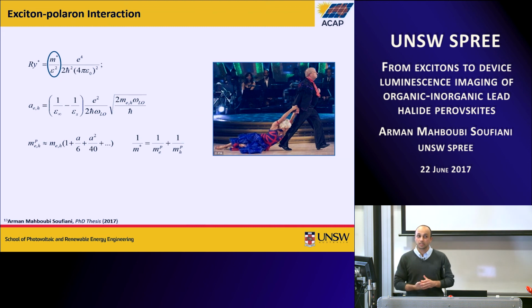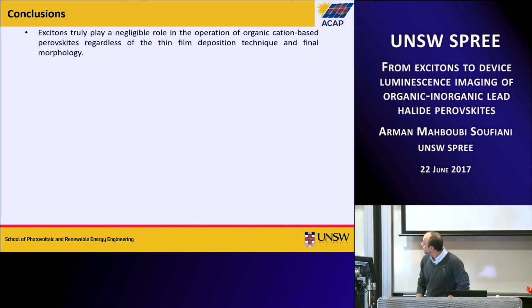And this polaronic effect is one of the reasons that the charge carrier mobility in perovskite is limited when you compare it to, for instance, gallium arsenide. Anyhow, I hope that I have convinced you. So the binding energy that I showed you was around 13, 16, and all these measurements were performed at 2 Kelvin, right? So 16, 13 at 2 Kelvin.